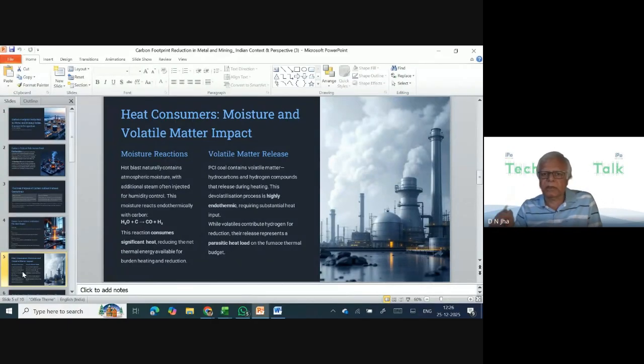So there are two things: that heating phenomenon, and the second portion is the reduction of the metallics. Once we say this, in this slide we talked about this very thing, that carbon and H2O reaction is a heavily endothermic reaction, and therefore any moisture that we add to the blast, or even if we are not adding steam to the blast, the atmospheric moisture is also something like 10 to 15 grams per cubic meter, and that 10 to 15 grams also takes quite some amount of heat in front of the tuyere to decompose into carbon monoxide and hydrogen.